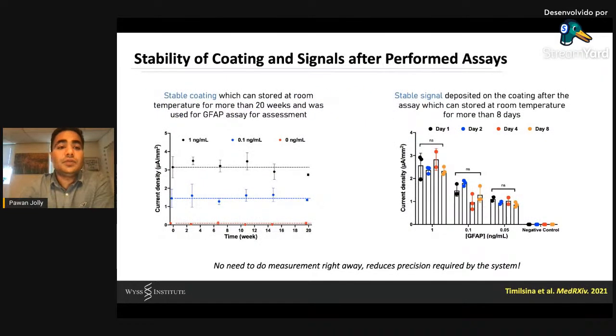Taking a step further, we actually also stored the coating for up to 20 weeks and performed assays just to assess the coating and the reliability of the coating. And as you can see over in the graph, just at room temperature, the coating was stable until 20 weeks. And I'm sure it would be stable even more, which is even good, because this coating can be further enhanced by just storing at cold temperature. Which you cannot really do with some of the tiles.